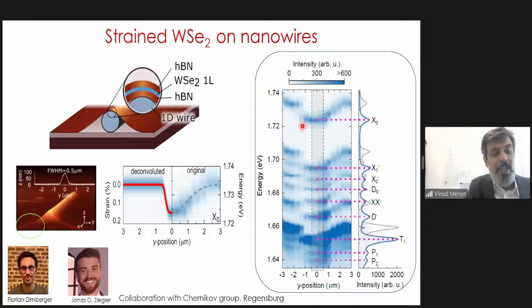Okay, so moving on, other ideas of increasing nonlinearity: strain. We usually don't like strain in semiconductors, but it turns out in 2D materials, strain is a very beautiful tool to play with. Here was an experiment that we started just when the pandemic started and labs were shut down. My postdoc Florian flew back to Germany where labs were still working, and he collaborated with the group of Alexei Chernikov and his student Jonas, and did this really careful experiment where he took a wire. It's a nanowire of gallium arsenide, only 90 nanometers in diameter, and he draped this 2D material on top of it. The 2D material drapes around like a tablecloth and introduces strain.